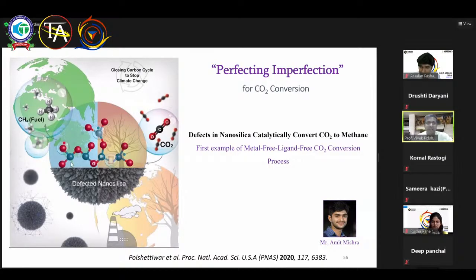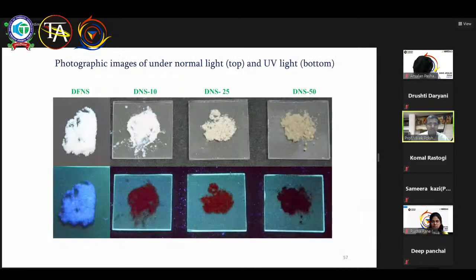And then we came up with this idea of creating defects in the material, and the defect itself then acts as the active site. In our case, silica is SiO2, so we removed some of the oxygen from the SiO2 and created two Si radicals and an oxygen vacancy where CO2 can sit. And the Si radical can activate the hydrogen molecule. That allowed us to convert CO2 to methane simply using silica, simply using the sand on your beach, ideally, obviously at the nanoscale with the defects, right? So this is one of the examples.